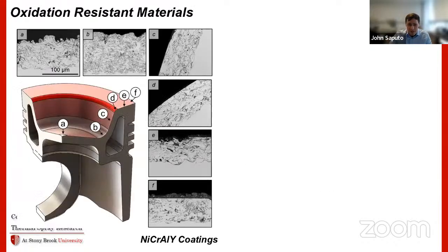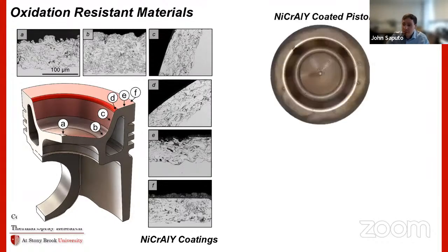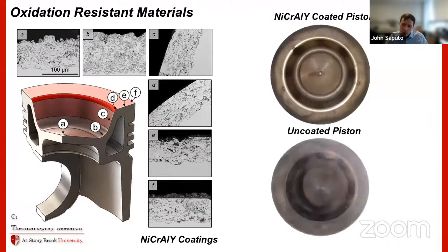So the first idea is that you can just slap an oxidation resistant coating on top of these things. So that's what we did. So this is a NiCrAlY coating that performs really well in these high temperature oxidizing environments, and we put it through that same degradation test, and it'll come out looking something like this. You compare that to an uncoated piston, and it actually looks kind of great. You can see it's still shiny. It does have some charring around that outside edge.